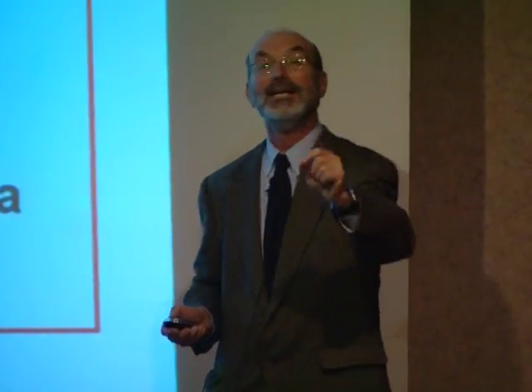And probably that takes you back to the subcritical crack propagation theory. Remember that if we have a very dry state, the velocity of crack propagation is very small, or 0. And you remember this K0 value in that reference graph that I discussed before, that marked the beginning of crack propagation. I said this is a threshold stress intensity factor. A threshold stress intensity factor translates here into a threshold confining stress. And we were actually able to find this threshold confining stress.